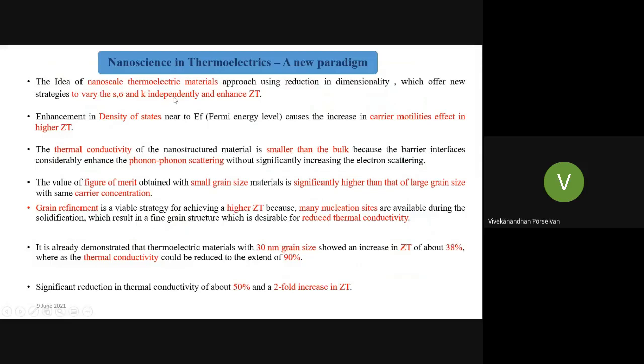So the idea of the nanoscale thermoelectric material approach is using a reduction in dimensionality, which offers new strategies to vary the S, sigma, and k independently and enhance ZT. Enhancement in the density of states near the Fermi energy level causes an increase in the carrier mobilities affecting the material. Thereby, it can achieve a higher ZT. The thermal conductivity of nanostructured material is smaller than the bulk material because the barrier interfaces considerably enhance the phonon scattering without significantly increasing the electron scattering.